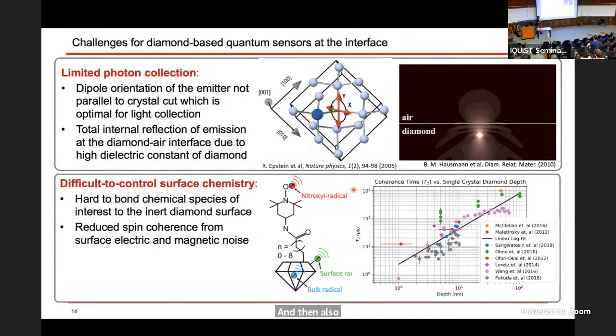these wide bandgap semiconductors that are host to good quantum emitters also tend to have a relatively high refractive index, so light actually tends to get trapped inside those crystals. And then if you're talking about using these quantum emitters for sensing, it's often difficult to control the surface chemistry in a way that will aid your measurements. Diamond in particular is a great stable material, but that also means that it's a very inert material, hard to functionalize. And there's also a lot of observation, all summarized in this plot here, that if you're dealing with near surface emitters, the closer you get to the surface, the more decoherence you have in your emitter, and that's just due to surface electric and magnetic noise.